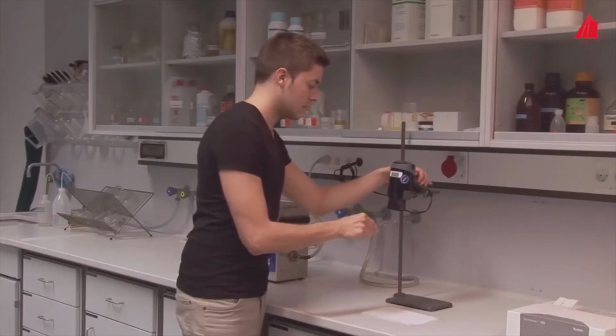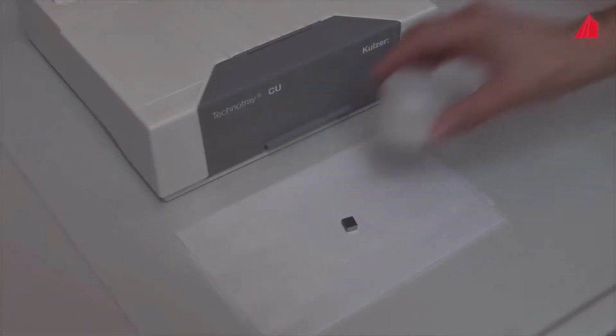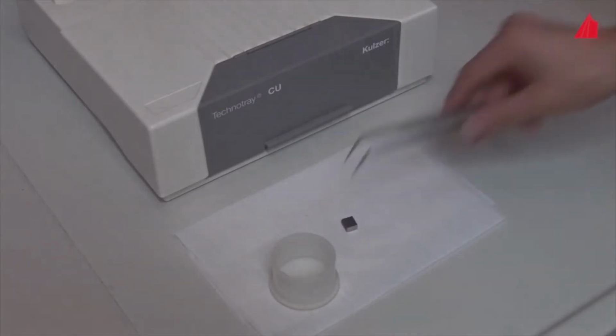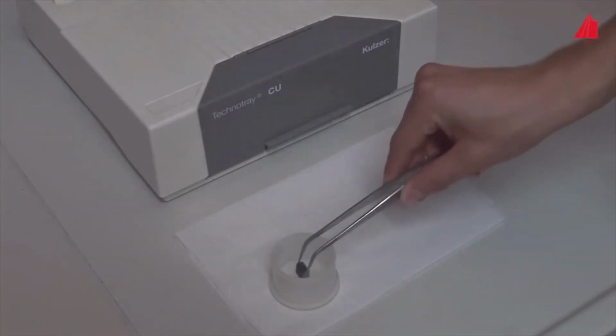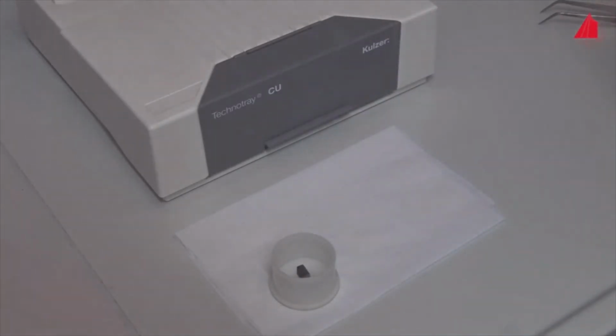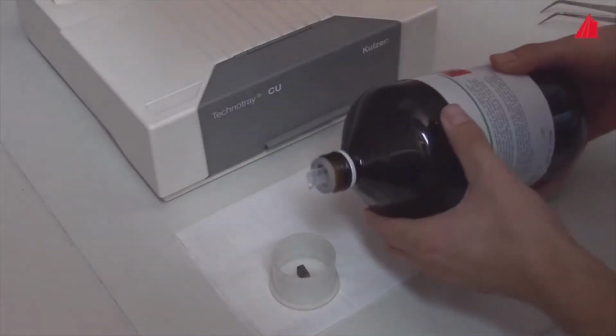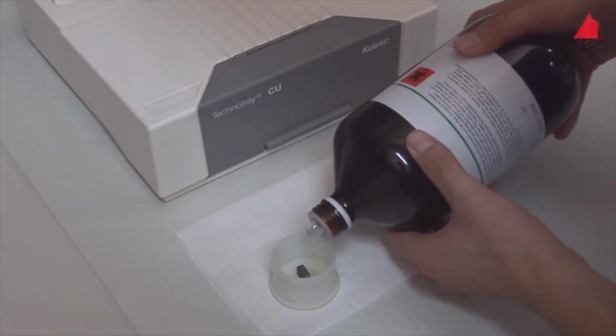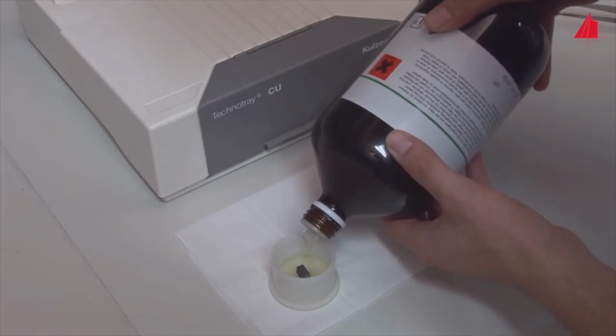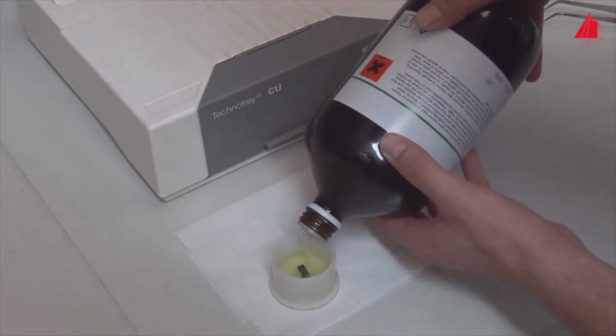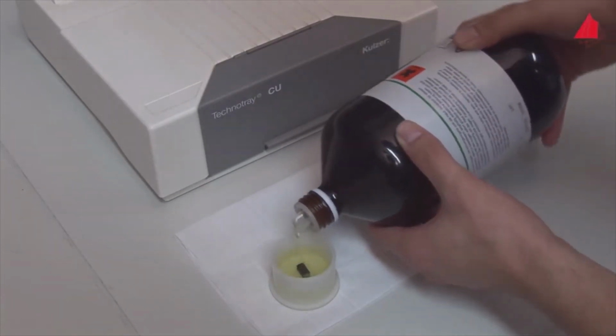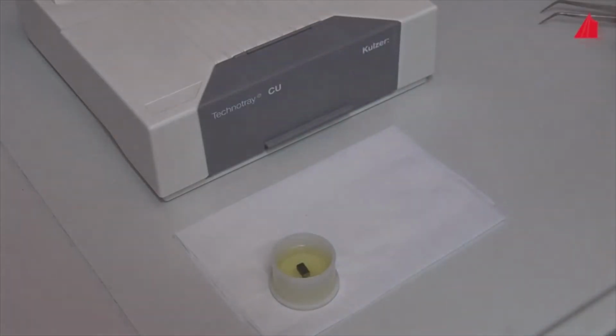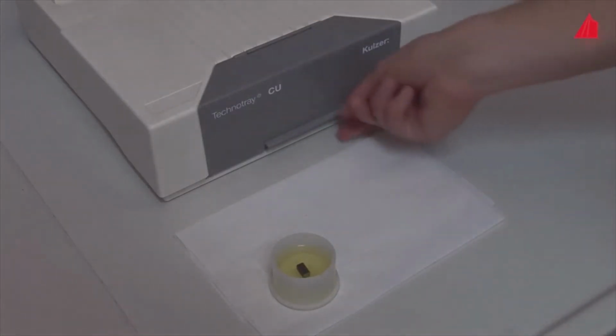To mount the specimen, small plastic molds are suitable. The material tester picks up the clean specimen and carefully places it into one of the molds. The intended plane of examination is at the bottom. Then he pours liquid resin into the mold. A thin layer of grease at the inner surface of the mold acts as a release agent. This ensures that the cured resin can later be released easily from the mold.